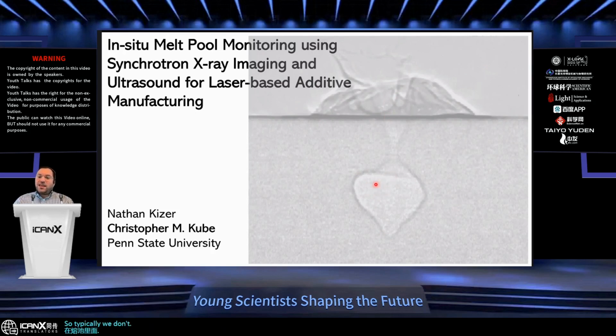Typically we don't want this gas. This gas leads to bubbles, and then when the metal solidifies, it leads to pores, and that leads to defects in your material, and it reduces the properties of your 3D printed metal part. So in this talk, I'm going to be talking about how we're using ultrasound to study the fundamental dynamics of these melt pools.